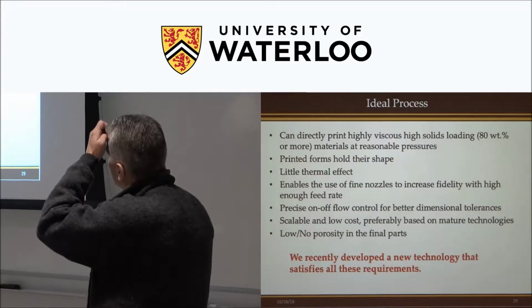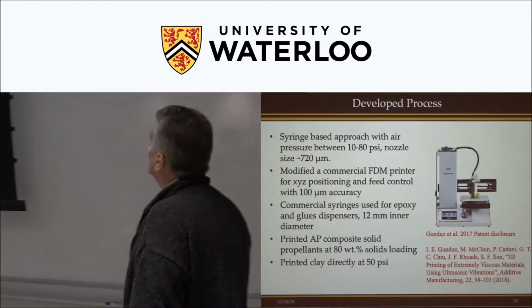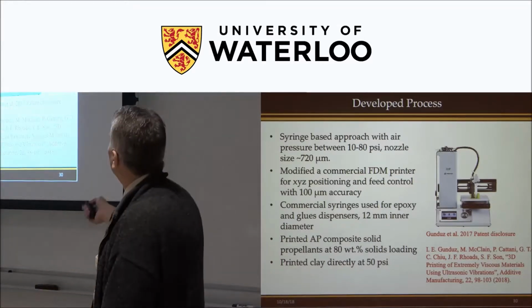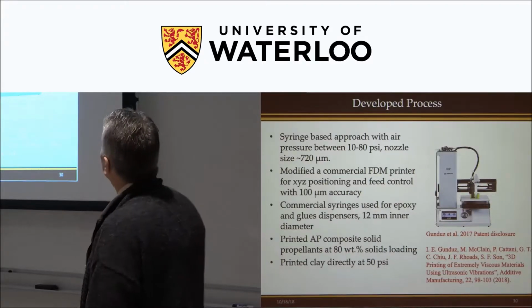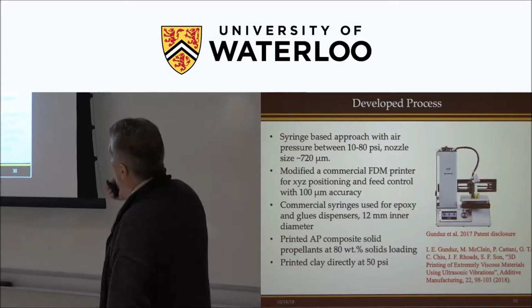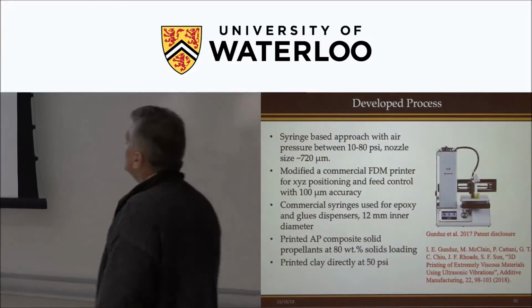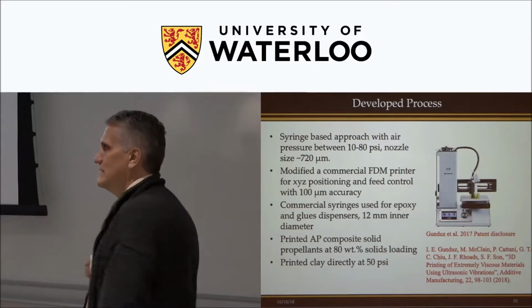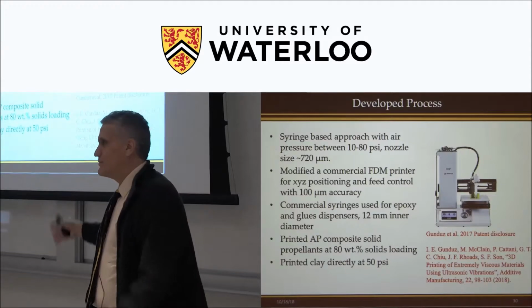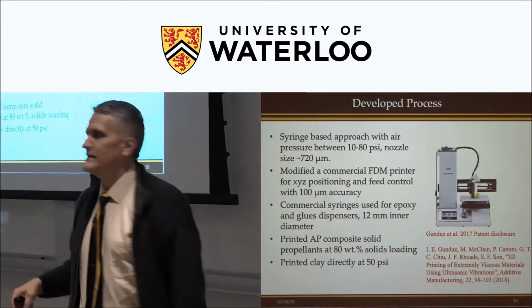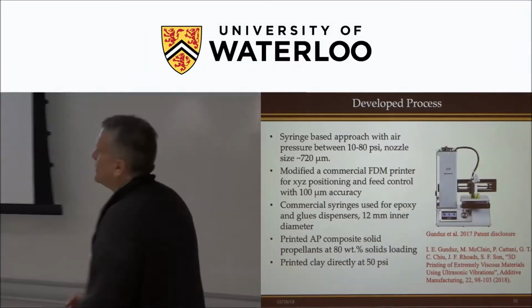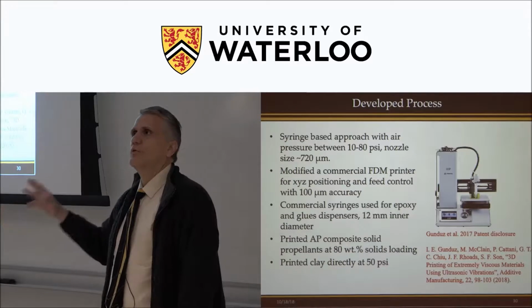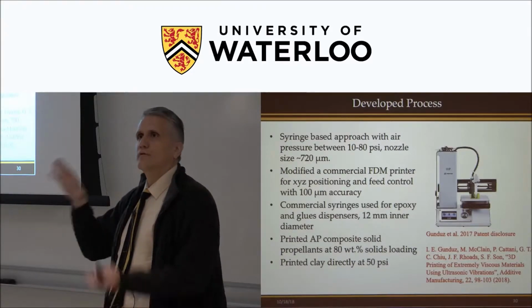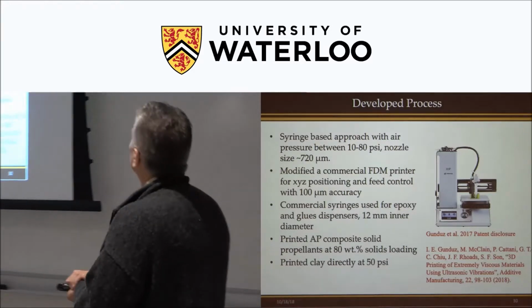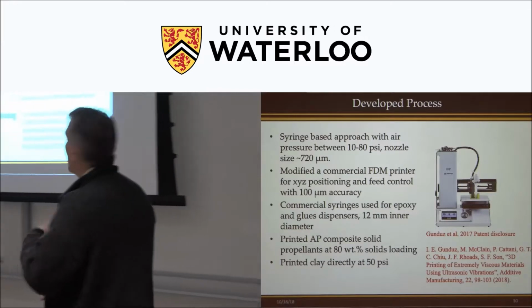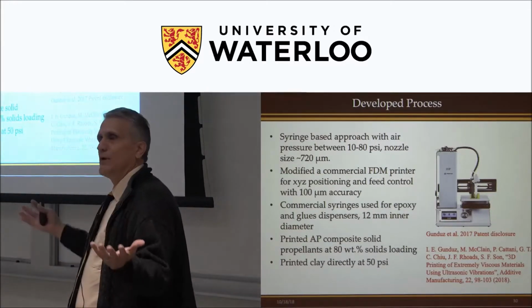So we developed a new technology recently that satisfies all of those pretty well. We started off with just a cheap printer. This is like a $400 FDM printer. We took all the FDM parts off and added a nozzle. We have a low back pressure. And the secret sauce is a vibration on the nozzle. People have looked at putting piezos and vibrating nozzles. This is nothing new. Well, how you do that exactly is new. And in addition, we use the vibration not only to enable the flow, but we actually turn the flow on and off with the vibration. So we have a low pressure that's not enough to move the viscous material. And then when we apply the vibration, that enables the flow. So you're all engineers. You probably learned this even in high school.